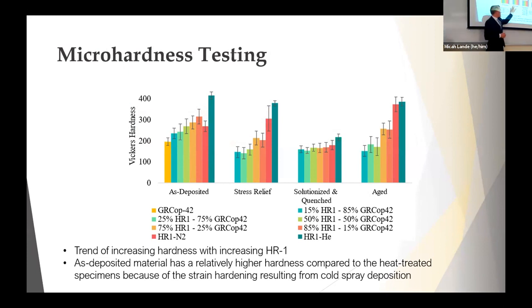And then as we go into the stress relief process, we see overall a lot of that is lowered by a pretty significant amount, mainly because after that stress relief, we're giving those particles essentially a chance to relax. They're able to reform their microstructure. And so that internal stress that is brought from the plastic deformation caused by cold spray, it allows that internal stress to be lessened a little bit. So we have better bonding, less internal stress, thus lowering our hardness.